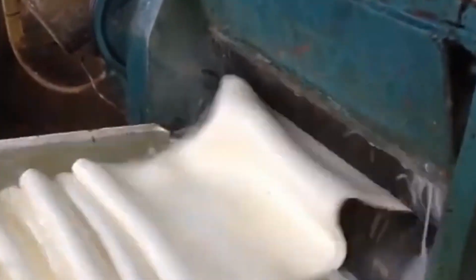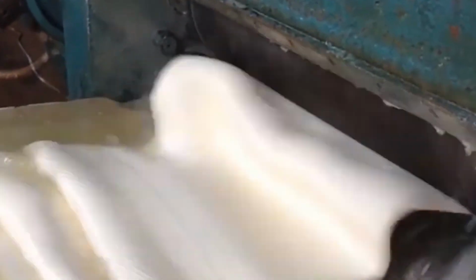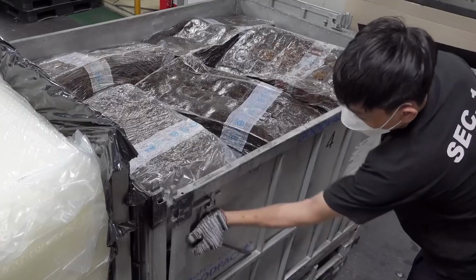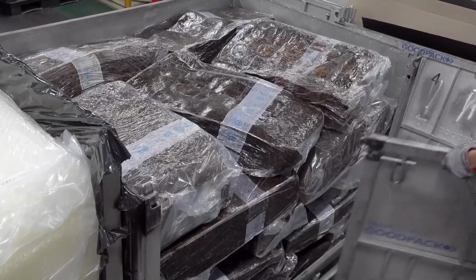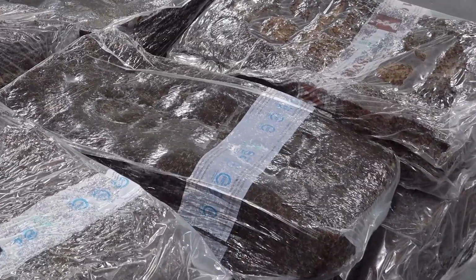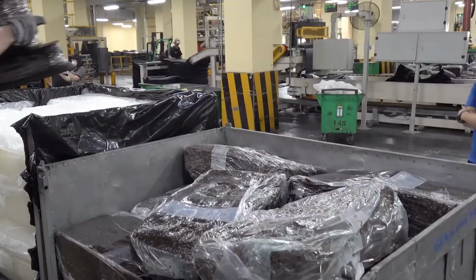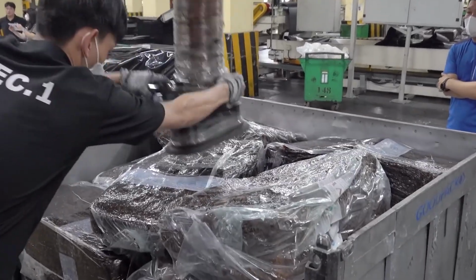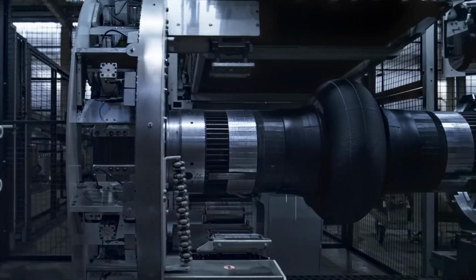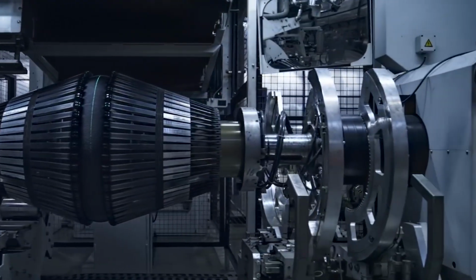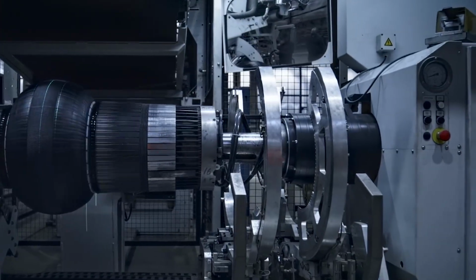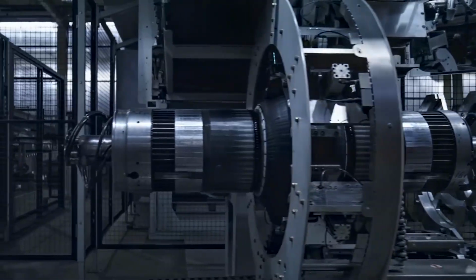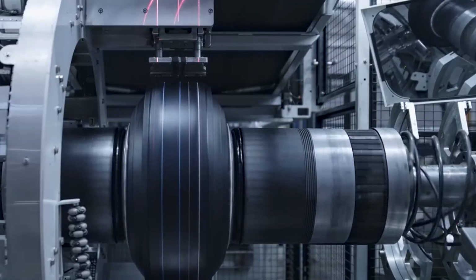The mold is closed tightly around the tire, and high-pressure steam or hot water is pumped into an internal bladder within the tire. This bladder expands, pressing the tire against the mold to shape it while simultaneously heating it to initiate vulcanization. The curing process involves heating the tire to temperatures between 140 to 160 degrees Celsius, 284 to 320 degrees Fahrenheit, for a specific duration, typically around 15 to 60 minutes depending on the tire size and type.